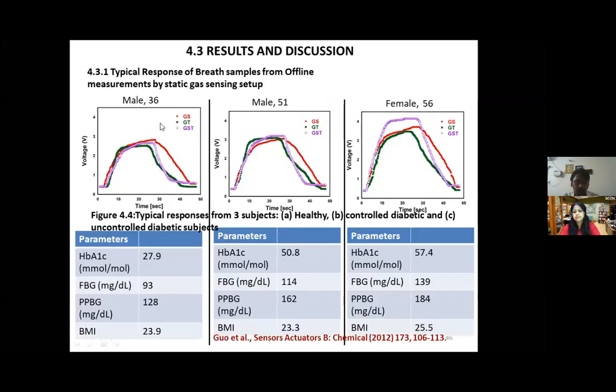And this is the typical response of the breath samples from offline measurement. That is, the patient blows into a Tedlar bag, we take a gas-tight syringe and inject it. So this is the saturation voltage, the typical response of all three sensors. As the HbA1c value increases, as the fasting blood glucose value increases, the saturation voltage also increases.